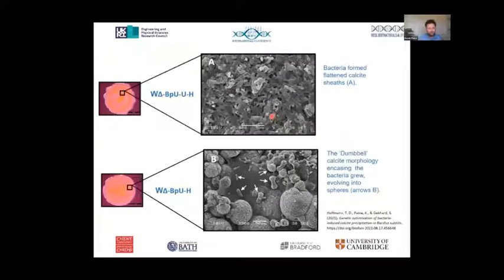But also what's really interesting is that when we looked at the calcite precipitation ability of both of these genetically modified bacteria, it was really interesting to see that the morphology of the calcite that they precipitated depended on the genes that they contained. So that really gives an insight into what's going on at a fundamental level in terms of calcite precipitation.